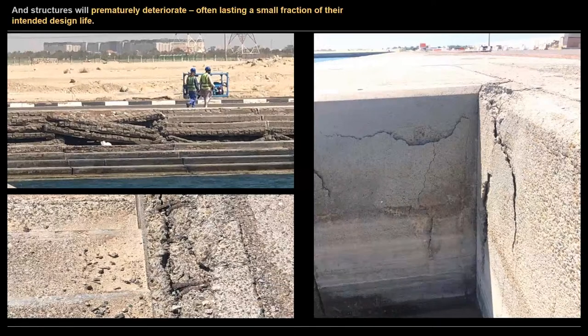These are just a couple of examples of concrete corrosion that I've taken from one of my Middle East presentations. This is a marine structure, a jetty in Abu Dhabi. It's 11 years old. It's a pretty extreme situation, very, very high temperatures, up to 55 degrees there. But that's the result of wetting and drying concrete in that sort of environment with very high salinity levels around the Arabian Gulf.